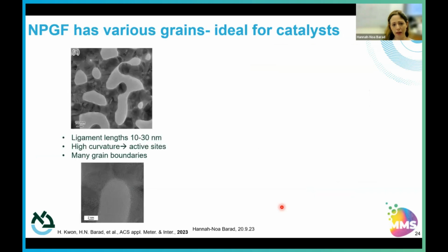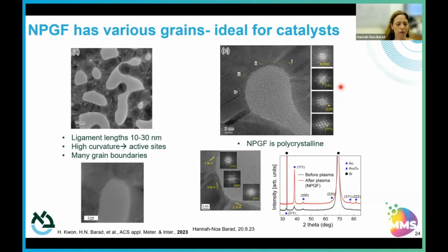And what's very nice about this, because of the mechanism of the way they coalesce, we're forming high curvature sites, actually, which are usually known to have high activity for catalysis. And you can see really lots of different types of grain boundaries. This is related to the coalescence mechanism, which is generally not seen for metals, for example, that go through the dealloying method. And we really have a variety of different planes that you can see over here.